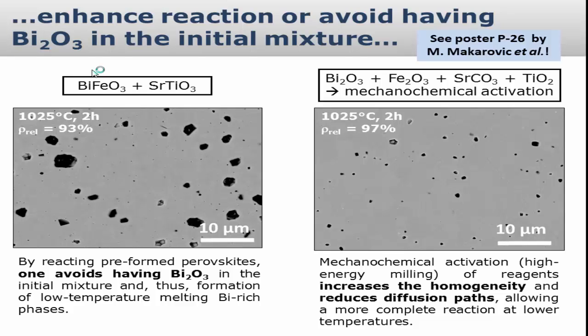And this we did by high-energy milling. It's basically a conventional milling technique in which you just don't add liquids, and you get a very homogeneous mixture. And it looks like we didn't see any liquid phase around the grain boundaries based on SEM. It's the same picture as I showed before, which tells you that probably these liquid phases will somehow react before they get melted. You can never get rid of the formation of secondary phases because you always have contacts there.